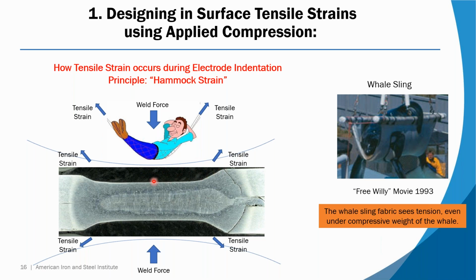If you look at the moment of indentation, you got this molten, squishy pudding underneath, and it's squeezing out, which allows for indentation. As that's going on, we're creating those hammock strains along the surface. If you had an initial point A and B on the parent metal surface, let's say there's a rope going across there, then when you indent, that rope has to get longer, right? Because now the shortest distance between two points is a straight line, but we've stretched it. So there's your tensile strain.